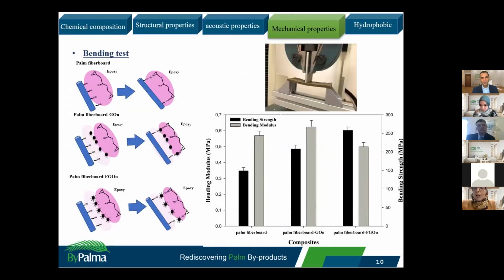So the mechanical properties of the composites are characterized by subjecting fiberboard with the modified and unmodified graphene oxide reinforced composite to a 3-point bending load, as you see in this figure. This figure shows the bending strength and the bending modulus of the prepared composite, which presents that the incorporation of graphene into fiberboard composites exhibits a significant improvement of flexural strength and modulus attributed to the well-dispersed rigid particles.